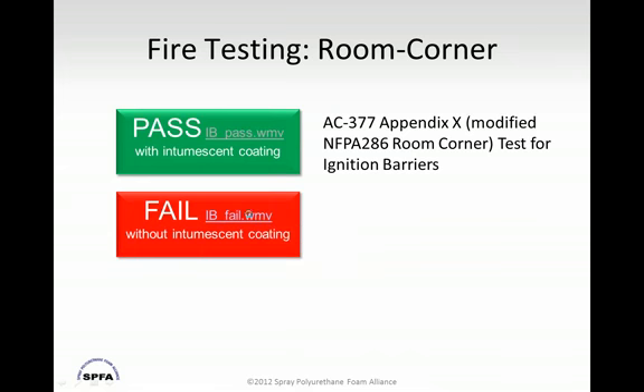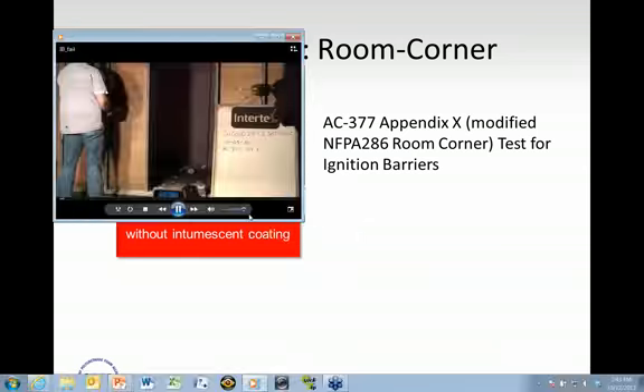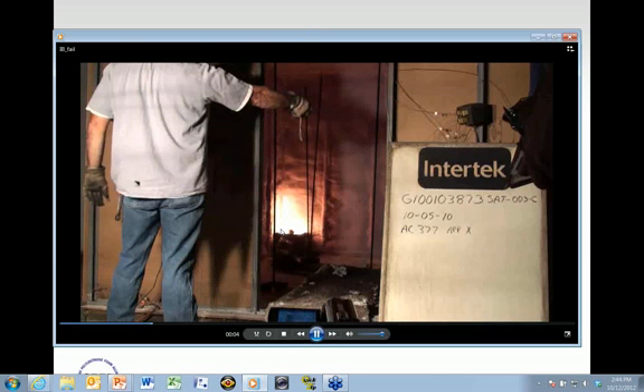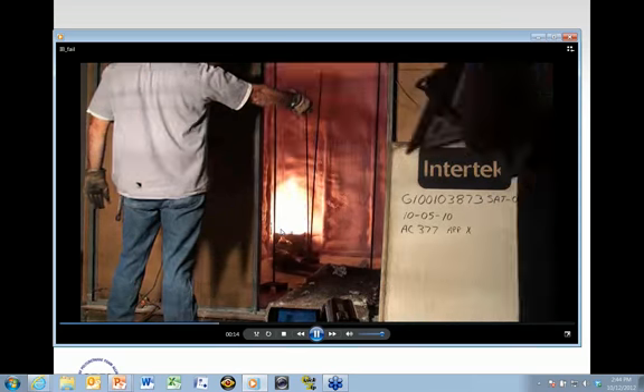I'm also going to show you what happens when you don't have an intumescent coating on the foam. Here again, this is the identical test without an intumescent ignition barrier coating for a particular foam. So you see the testing has started. The guy will move out of the way of the clock in just a moment. And watch the second hand here, because I'm not even going to move this test forward. We're about 10 seconds into the test.